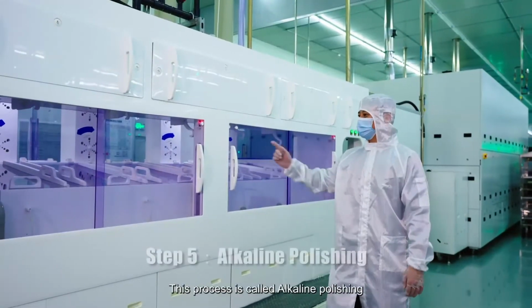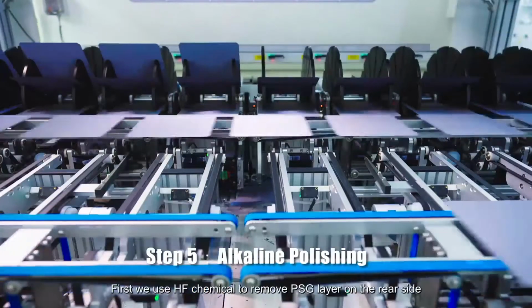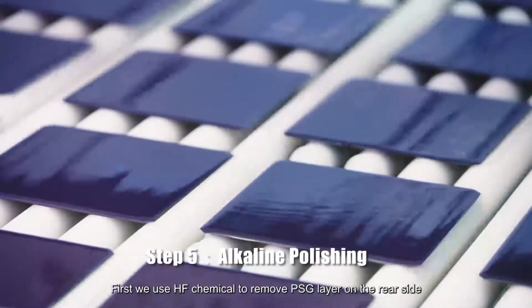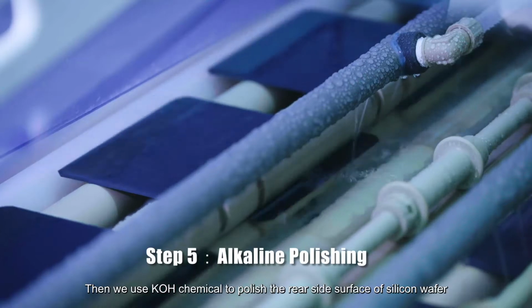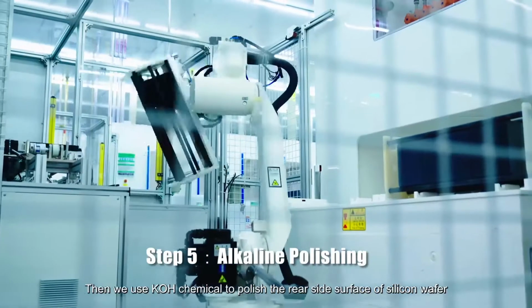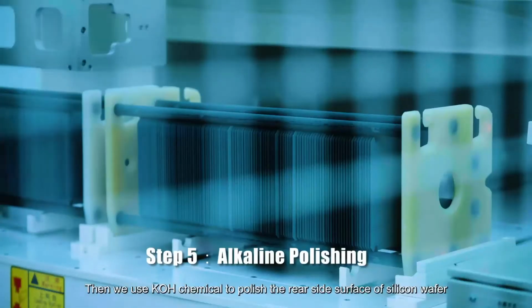This process is called alkali polish. First, we use HF chemical to remove the PSG layer on the rear side. Then we use KOH chemical to polish the rear side surface of the silicon wafer, preparing for passivation layer deposition afterward.